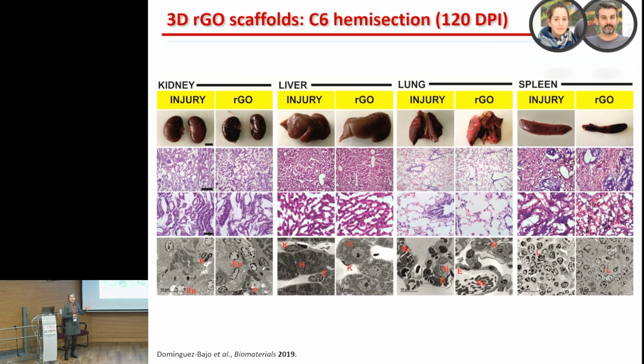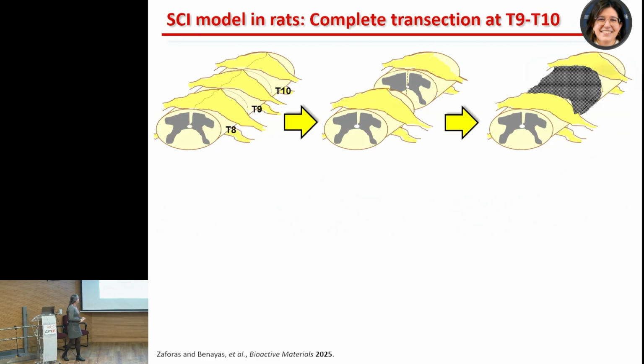So another important point that we need to check at that time, and that we continue doing, is the toxicity. There were no signs of systemic toxicity in these rats after 4 months of implantation. We checked the main organs, you see here, and also some other organs like the heart and the intestines, and we couldn't find any damage. So this was the starting point for Esther and for her PhD work. And she challenged the system a little bit further.